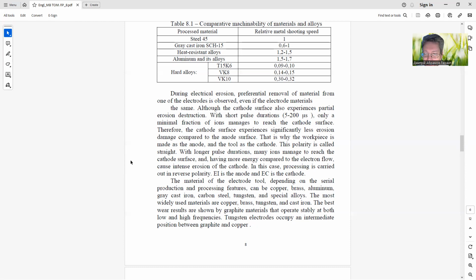With longer pulse durations, many ions manage to reach the cathode surface and, having more energy compared to the electron flow, cause intense erosion of the cathode. In this case, processing is carried out in reverse polarity. EI is the anode and the workpiece is the cathode. The material of the electrode tool, depending on the serial production and processing features, can be copper, brass, aluminum, gray cast iron, carbon steel, tungsten, and special alloys. The most widely used materials are copper, brass, tungsten, and cast iron.